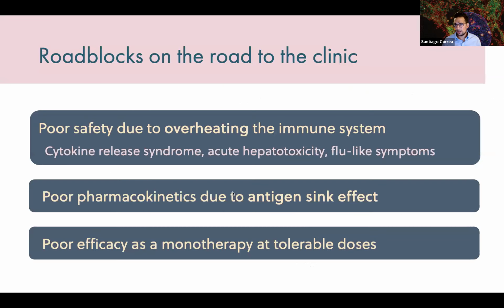Despite the fact that this antibody has been around for quite a long time, it still hasn't been translated into the clinic. And a big reason for that is toxicity issues, similar to what was holding IL-12 back. But in addition to that, this antibody binds to a surface receptor, CD40, that exists on immune cells that are all over your body. So that creates what's called an antigen sink, which means that within 24 hours, this antibody is actually no longer detectable when you're in circulation.